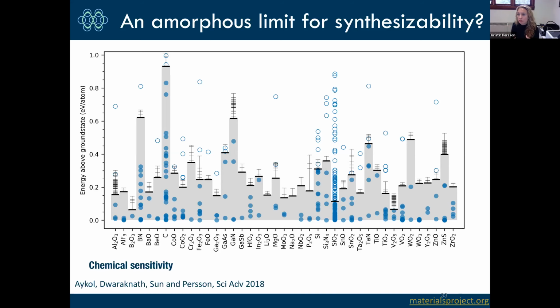So all the filled circles are materials that have been made, have been synthesized, and survive under normal standard conditions. And all the empty circles are things that have never been made or have been made at some weird conditions, and once you actually release the pressure, they amorphosize. So we believe we have found at least a metric to screen out particularly bad ideas. As you can see, the energy scale here is pretty large, 200, 400, 600. So it's not tremendously sensitive in the energy scale, but it is much more sensitive when you look at the differences in terms of different kinds of chemistry, the compositional sensitivity.